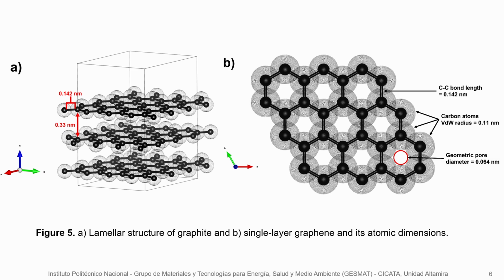Recently, investigations on graphene materials have shown that they have the potential to be used as a barrier in nuclear environments. This is because the carbon lattice of graphene has a very tiny geometric form, and this can help to avoid helium penetration. Also, graphene has a very low sputtering yield and is very flexible and is a very hard material.